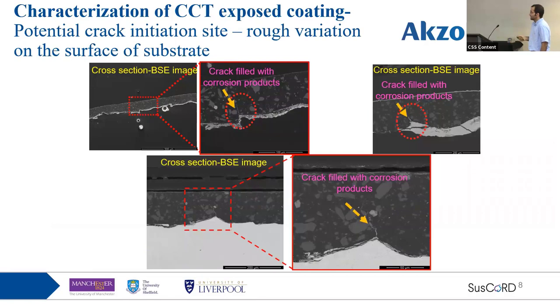There is a third initiation site that we identified, and that correlates with the substrate. When we have a rough substrate, that rough substrate may create the conditions for a fatigue crack to form within the coating due to the cyclic exposure test. These samples I am looking at are coatings which were not removed from the scratch; these coatings are from the near-scratch regions. As you can see, wherever I have a rough surface, I could see a crack has formed and corrosion product has penetrated into these regions.